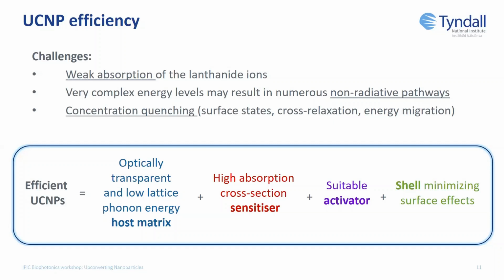So when we talk about efficient upconverting nanoparticles, what we would really like to see is an optically transparent and low lattice phonon energy host matrix. We would like to see a high absorption cross-section sensitizer. We would like to see a suitable activator, and by suitable activator, I mean an activator that matches the intermediate state of your sensitizer, first of all, and that is optimized for emitting the wavelengths that we need for our application.